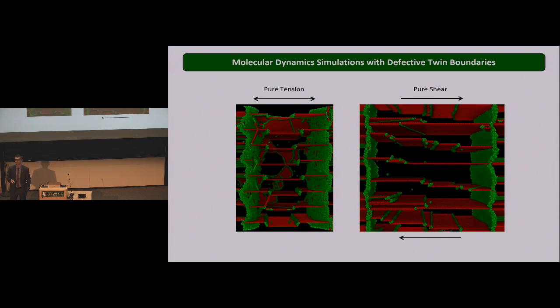Yes? We're looking at complete lattice dislocations, not the partial dislocations associated with the boundary. I don't get your question. Shear a twin with the passage of partials. Mm-hmm. That's not what's going on here. These are the pre-existing twin boundaries. So they are stacking faults, okay? And so these are just defects along the stacking fault. So we're not creating new dislocations in the pure shear model. The defects are just migrating naturally along the plane of the twin boundary. So they are not new lattice dislocations, okay? So there is definitely a new mechanics associated with that.